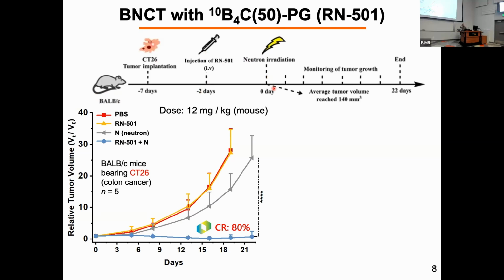That means it gradually, slowly accumulates and is not quickly removed. At the highest concentration, observed after 2 days, we start to irradiate with neutrons. This is the result for the relative tumor volume, starting from 1. The control groups are just PBS, phosphate buffered saline, without any drug, only the drug, or only the neutron irradiation. And then the material injection plus neutron irradiation.